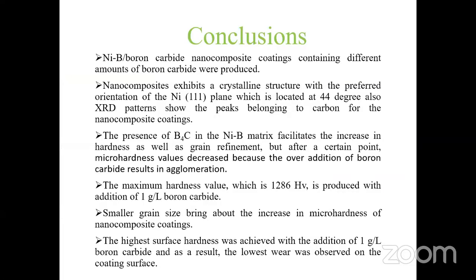Conclusions: nickel boron boron carbide nanocomposite coatings containing different amounts of boron carbide were produced. The nanocomposite exhibits a crystalline structure with the preferred orientation of the nickel 111 plane, which is located at 44 degrees. Also, XRD patterns show the peaks belonging to carbon for the nanocomposite coatings.